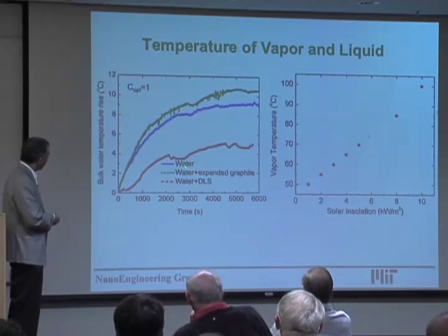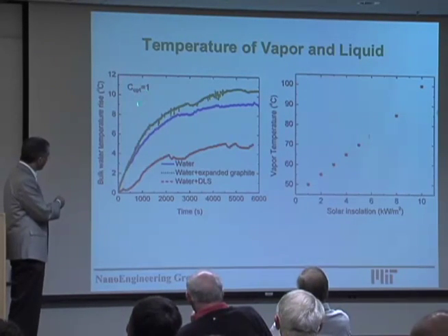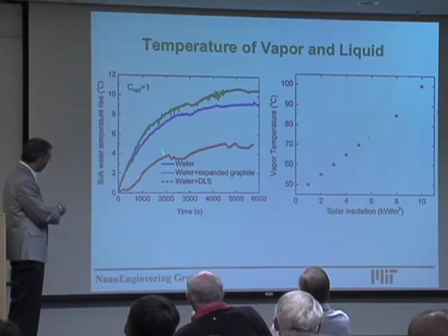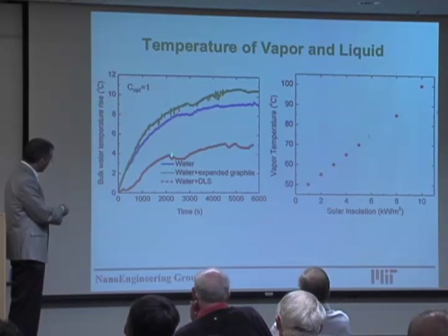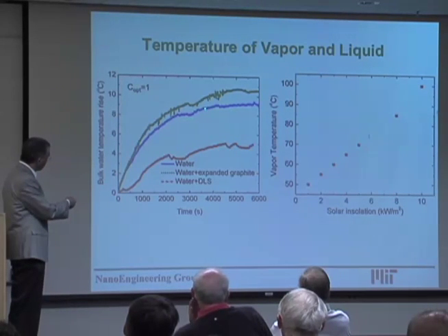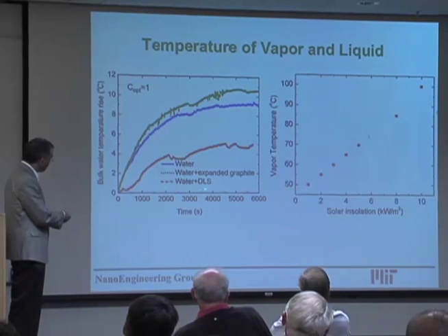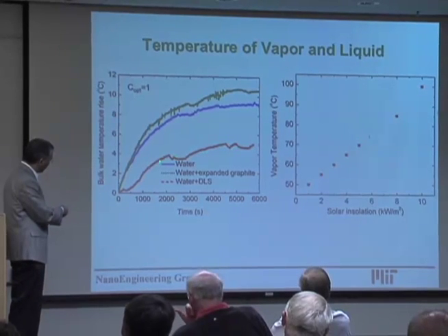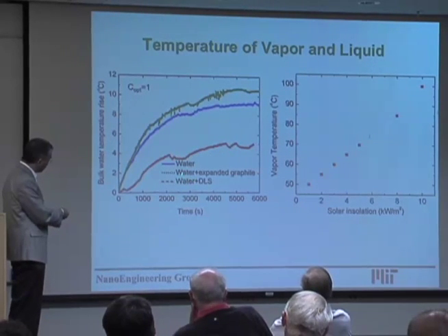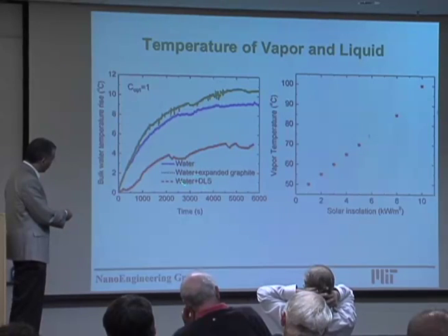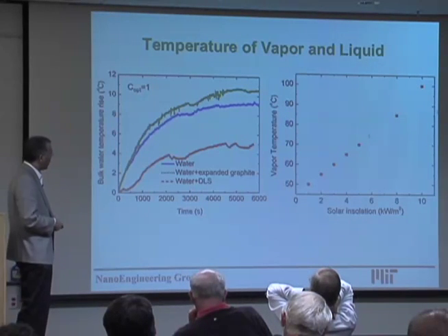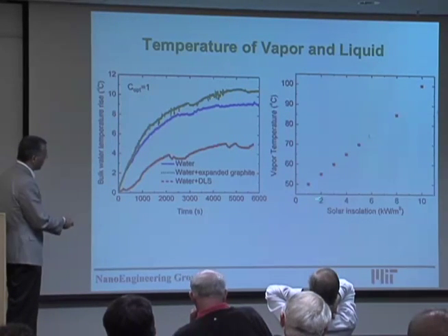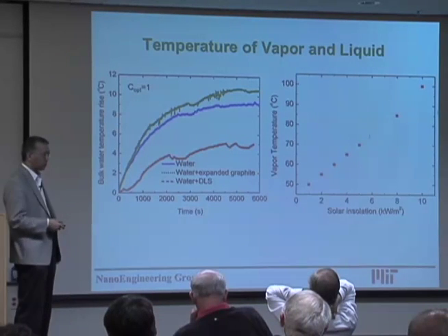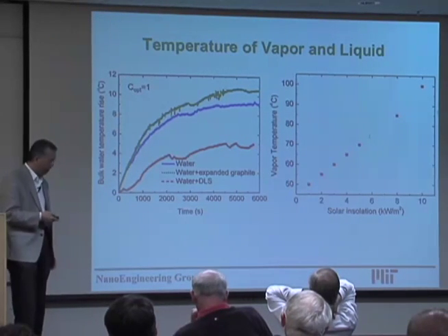And if we compare under 1 sun condition, this is the water temperature, right? If you just don't have any absorber there, water is here. And when you use the double layer structure, in fact, because most of the solar radiation is absorbed in the top layer, the water is cold. And under different concentration, the vapor temperature increases.